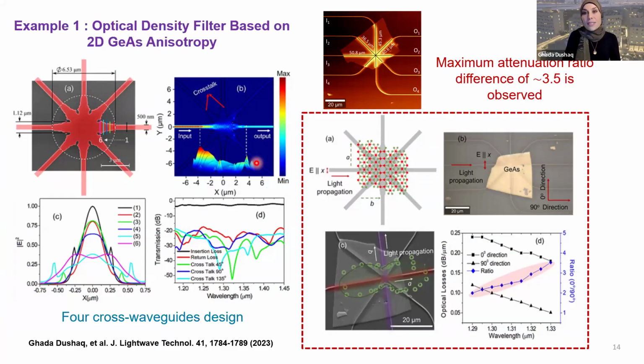So we stamped this material onto a four-waveguide crossing, and you could see that, depending on the crystallographic orientation of this material, you can channel the light differently. So you can attenuate the light in a different way just by rotating this flake because of the absorption-dependent crystallographic orientation dependency. And this is very useful because, using the same material, you can pass the light in different channels, but it attenuates at the output differently.